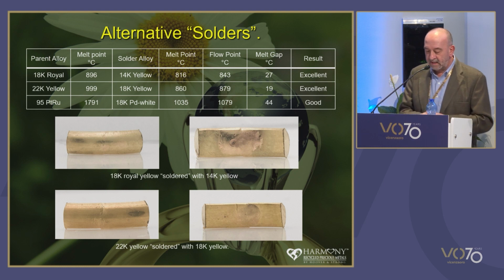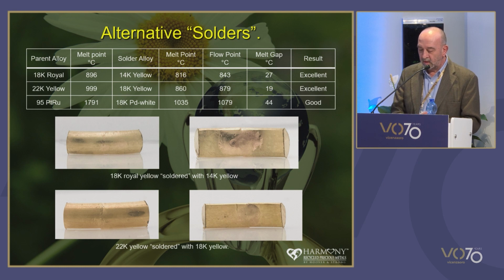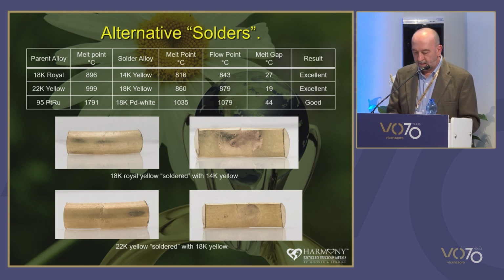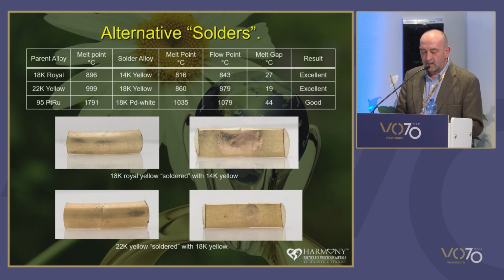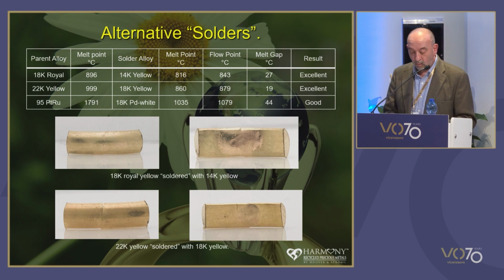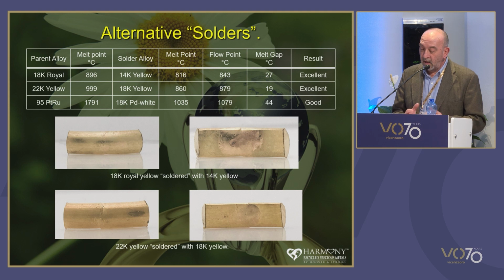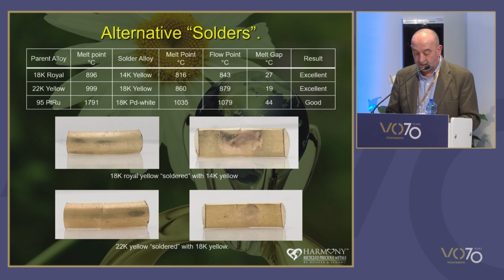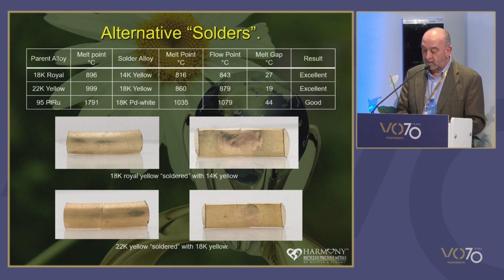So there's a 53-degree difference between the liquidus of 14 yellow and the solidus of the 18 yellow, and the 14 yellow has a 27-degree melt gap. And using flush joint faces, the results were excellent. So the same applied when we soldered the 22 karat yellow gold with 18 karat yellow gold. All the criteria for a solder were met and the results were achieved. A little bit not so good on the 18 palladium white doing the platinum, but those results were also acceptable. So this really showed us that you do not need special solder formulas for things to act as solders. All you need to do is fulfill the criteria and the operation should work.